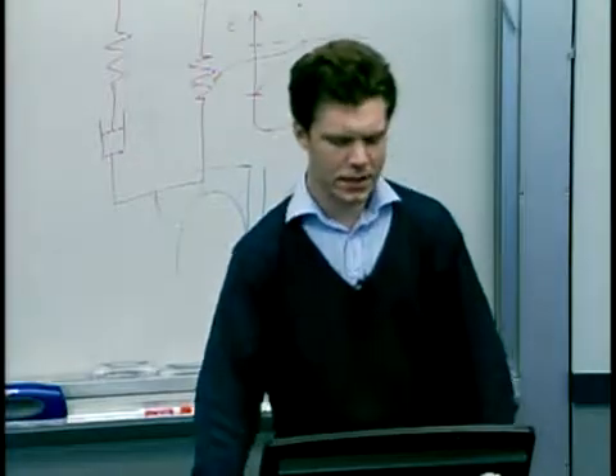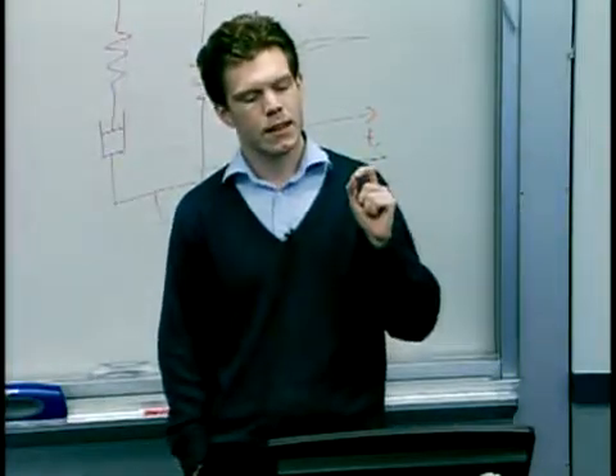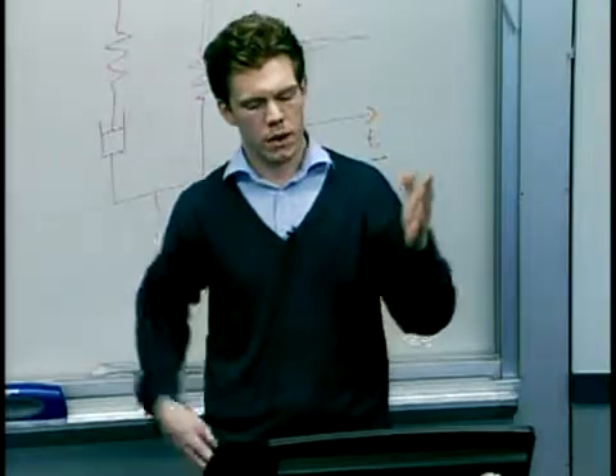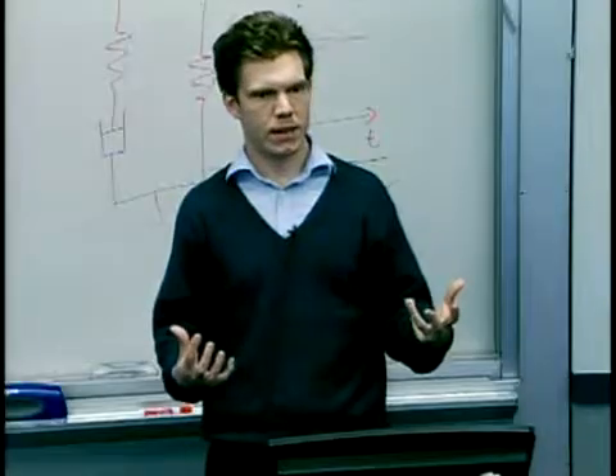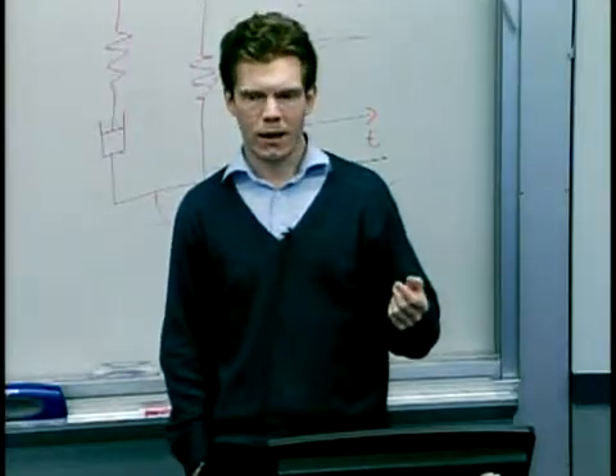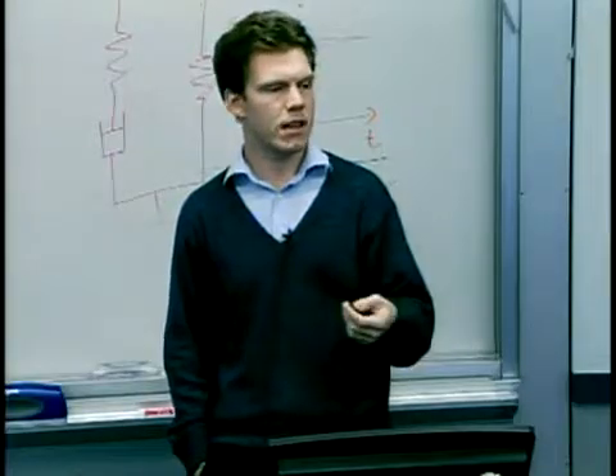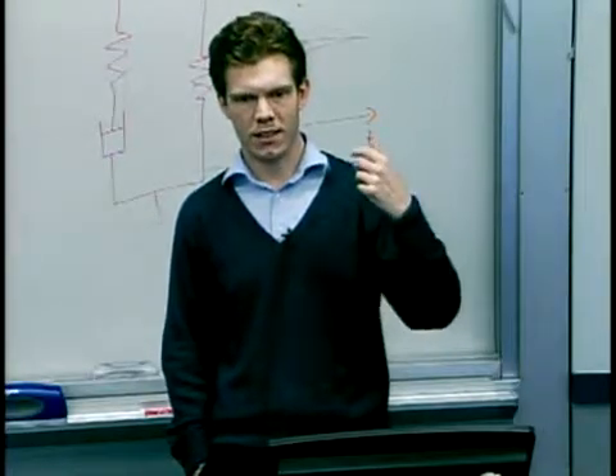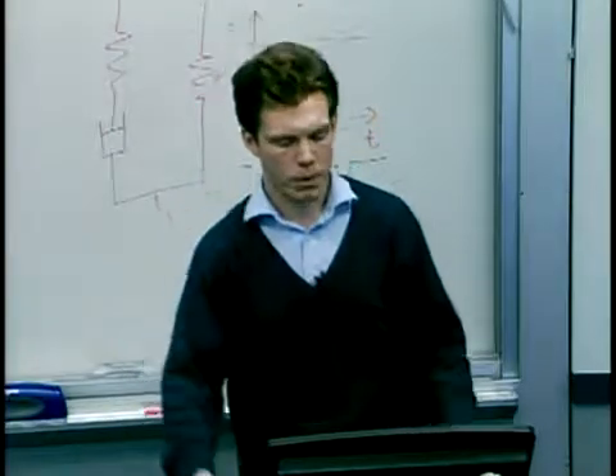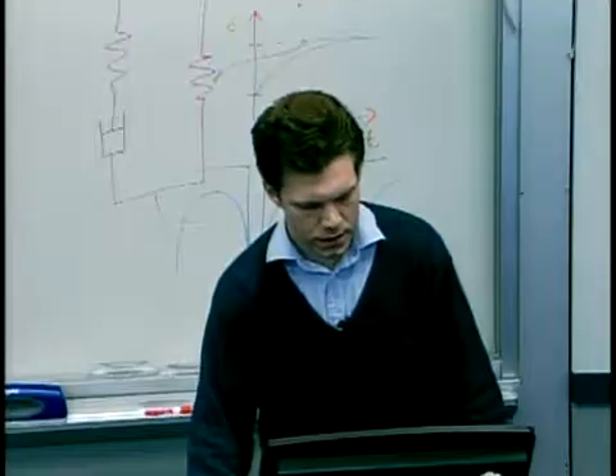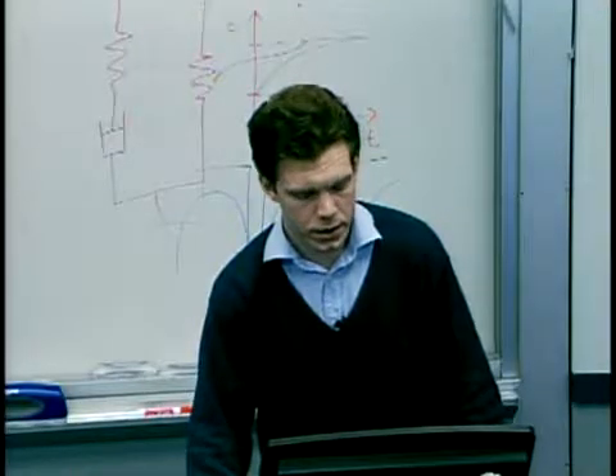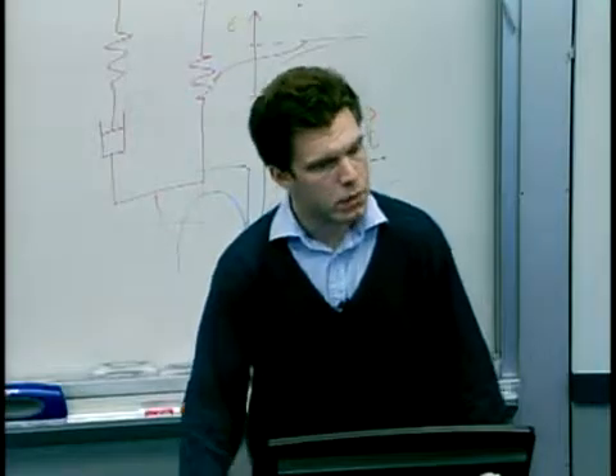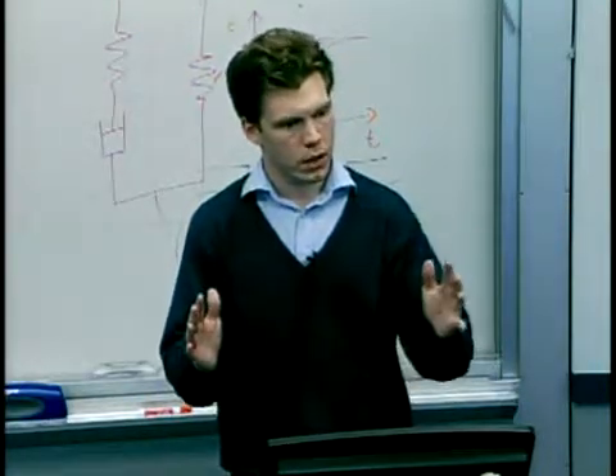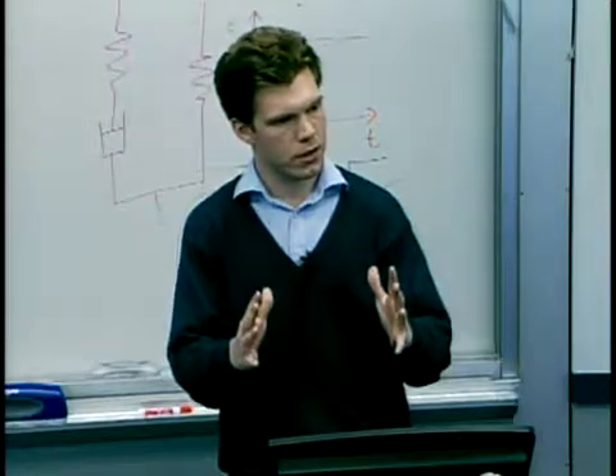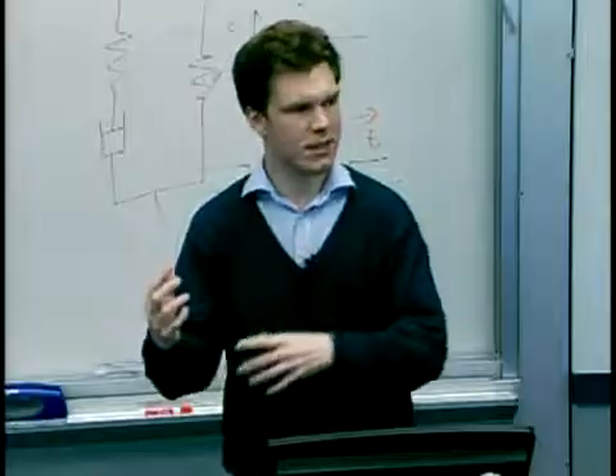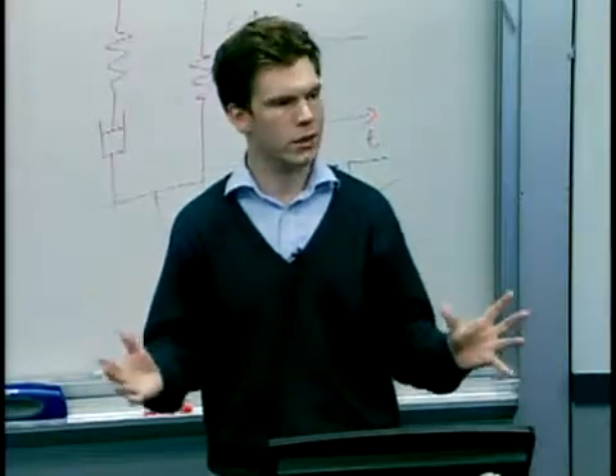I should have highlighted when I showed you this graph that there are trade-offs to be made in picking these operating parameters. On the one hand, you might say, I don't want to heat the material any hotter than is necessary. I'd rather just press as hard as I need to, and maybe operate at 120, 115 degrees C, where I can deform the material. And then, because I'm not at a very high temperature, when I cool down, there isn't going to be very much differential thermal contraction of the stamp and the substrate. So I won't have big residual stresses, and I won't risk breaking the stamp.